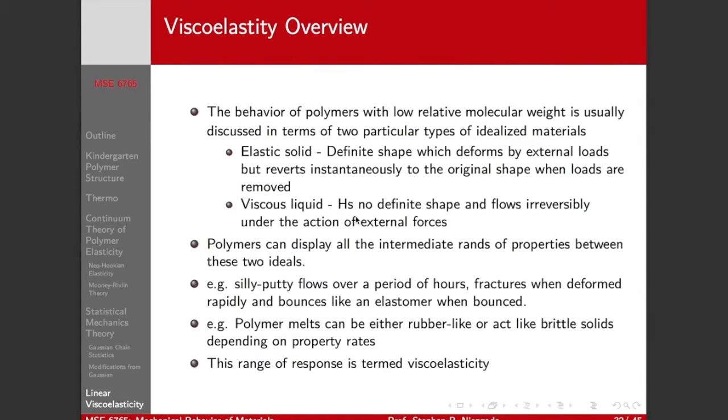Polymers with low molecular weights will often have a very strong time dependence to their loading. And so we can break up the behavior into two parts. First, the elastic solid, that's a definite shape which deforms by external loads and reverts instantaneously to the original shape when the loads are removed. And they also behave partially like a viscous liquid. No definite shape and flows irreversibly under the action of external forces. So polymers can be anywhere in between, depending on the molecular weight, the temperature, solvents.